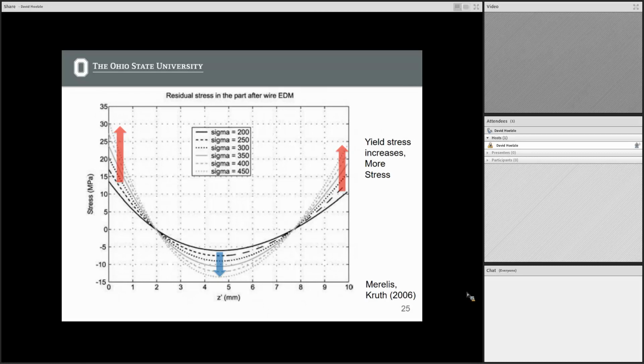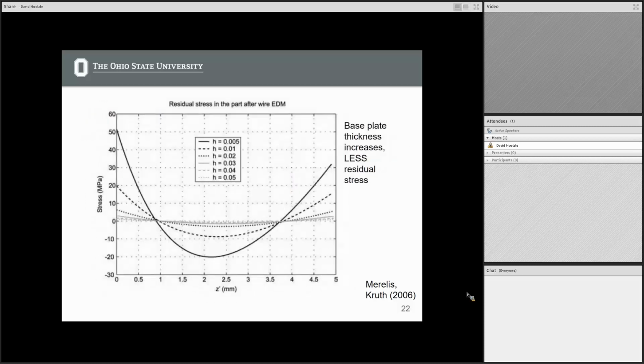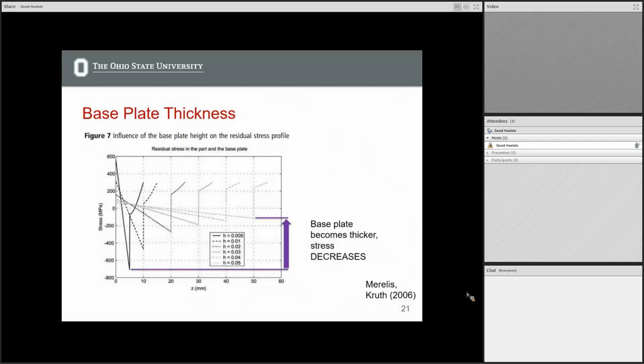I mean, they were showing reduced or increased residual stress with an increase in build plate. So let's see, increase in build plate height. Yeah, so if you increase your build plate thickness, you're going to be getting a reduced stress. So if you make your build plate stiffer, you're going to begin to reduce that residual stress. This plot is interesting, but no one would ever print on a build plate that's only 5 millimeters thick.